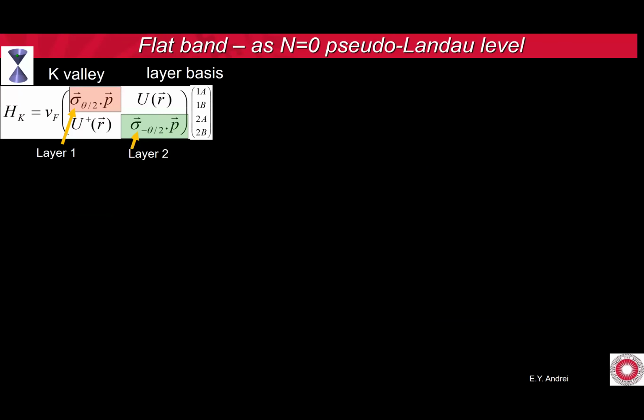Okay, so how do we see that this looks like an n equals 0 pseudo Landau level? If we look in, let's say, one valley, the K valley, and we write down the Hamiltonian, you have 2 blocks. This is the Dirac bi-Hamiltonian. Sigma is the Pauli matrix that operates on the sublattice degree of freedom, sigma dot P on the top layer, sigma minus theta 2 dot P in the bottom layer, and these U's are the interlayer tunneling operators. And this is in a layer basis, okay?